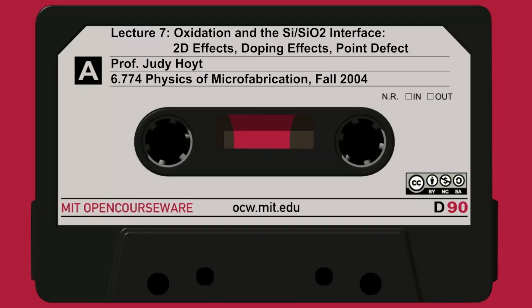So let's go on to slide 23. This generation of interstitials is extremely important because it is used to explain the non-local effects of oxidation, such as oxidation-enhanced diffusion, which we'll show, or oxidation-retarded diffusion. And it's because the interstitials can diffuse very far from the interface and change the diffusivity of dopants. So this shows how these models can actually be used. At this interface, about 1 in 1,000 of the oxidized silicon atoms is injected into the bulk. So for every 1,000 atoms that I oxidize, 1 atom goes into the bulk that wouldn't be there ordinarily if I were not oxidizing.